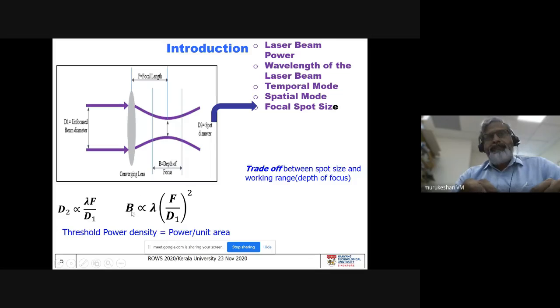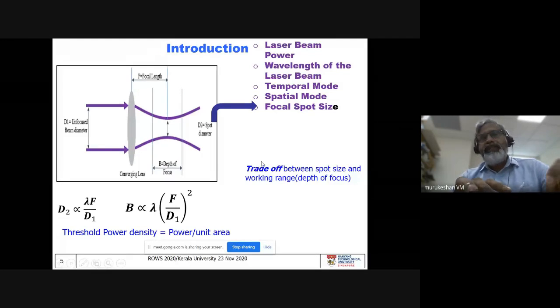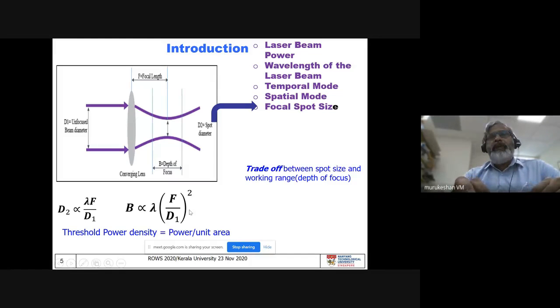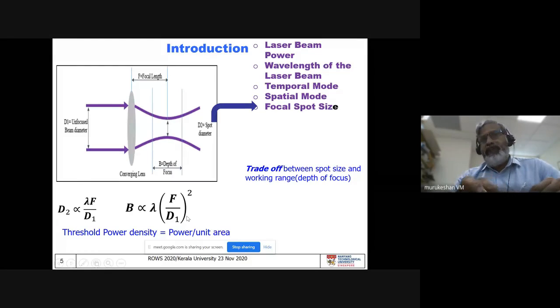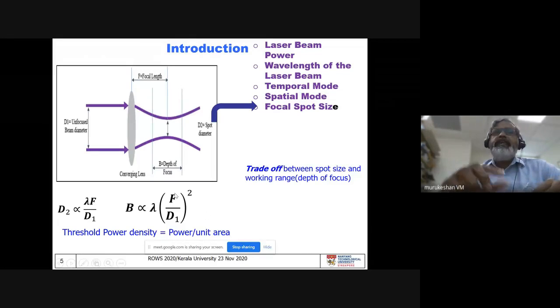But you see that this B is directly proportional to this wavelength of light, and directly proportional to the square of this ratio between the focal length to the unfocused beam diameter. So while we are trying to reduce this focal spot size to increase the power density, we eventually reduce the depth of focus. So there is always a trade-off between the spot size and working range. So in such context, depending upon the application, we need to optimize these two parameters, which are very, very important, which eventually tells us that the achievable focal spot size is actually